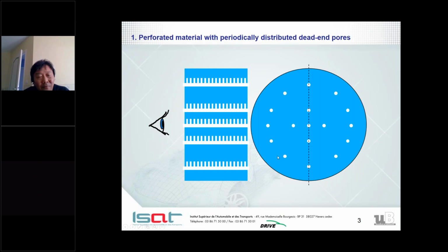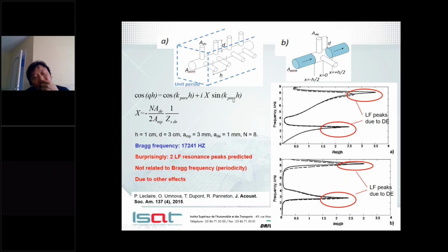And for the theoretical part, we thought to model this, of course, as a single perforation with periodically spaced lateral cavities, but we also had to account for the fact that we could have several at a given node. This could be called a node. We could have several cavities at a given node, and so we tried to model the structure. In the modeling, we ended up with the dispersion equation, which is quite simple, while the resolution of this equation is not that simple, but the equation itself is all right.